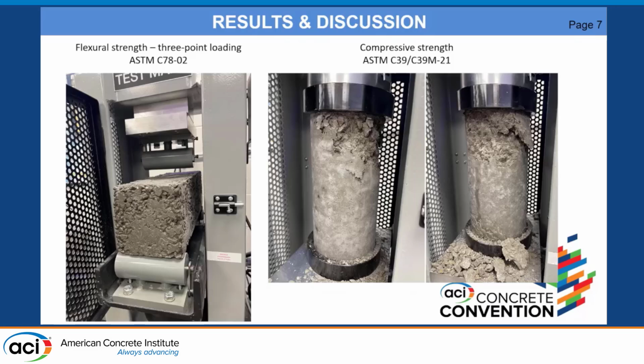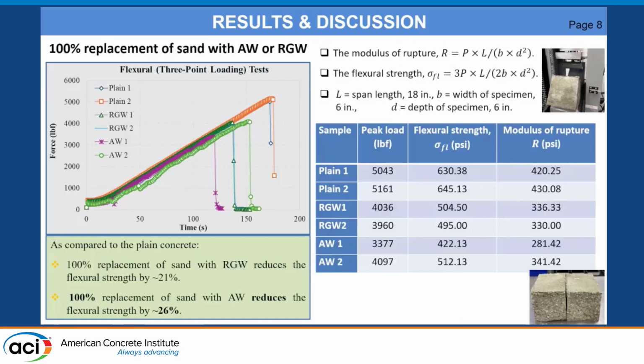And then this is our testing apparatus here. You can see some of the beams being crushed there. We got pretty nice failure modes from them, so that was good to see. So looking at the results for 100% replacement of both alumina waste and recycled glass, you can see the plain